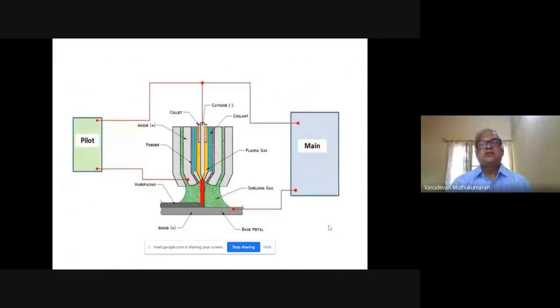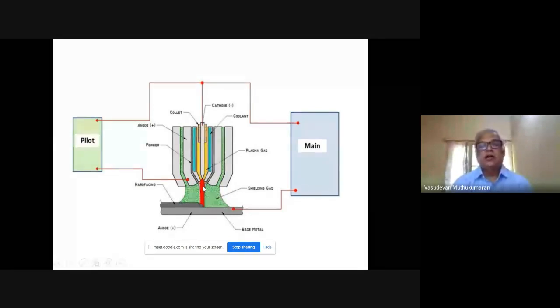This is how the plasma transferred arc process works. You can see here the tungsten electrode, and the inner nozzle and outer nozzle. In the outer nozzle we have shielding gas. In the inner nozzle we have plasma gas, and powder is also fed through this. When the arc comes through the nozzle, it gets constricted. That's how it gets a penetrating arc, and the process performance is enhanced. You can see the hardfacing deposit laid on the substrate material. This is the process principle.